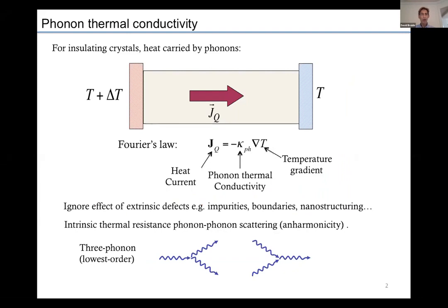Okay, so diamond is a crystalline insulator, so we're going to be interested in studying thermal transport in insulating compounds where heat's carried by phonons. We're going to ignore the effect of extrinsic defects like impurities and boundaries that can scatter phonons, and focus instead on just the intrinsic thermal resistance that's produced by the interaction between phonons, which comes from the anharmonicity of the interatomic bonding potential. And to lowest order, this interaction is between 3 phonons, and that tends to dominate the thermal resistance. So that's going to be our focus for a lot of the materials we've studied in any case.